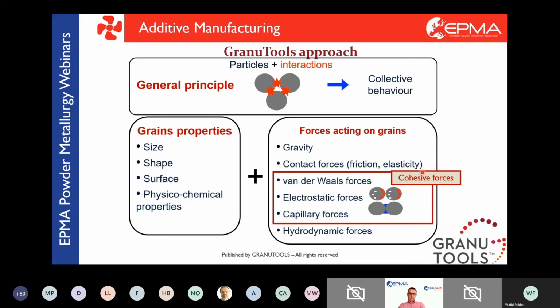And if you take granulated sugar or flour, you can see that the flow properties of those two powders are different. And the reason is that some particles are sticking more than others. So there are three cohesive forces: the van der Waals forces, which are due to chemistry, so you cannot do much about them; the electrostatic forces that can build up in some processes, so it is quite an important topic; and the capillary forces, which are due to humidity inside the powder. So this is what we want to characterize, the cohesive forces, and we can assume that if the cohesive forces are low, then the powder will flow well and therefore spread well, and if they are high, then it will not flow that well and so not spread that well.